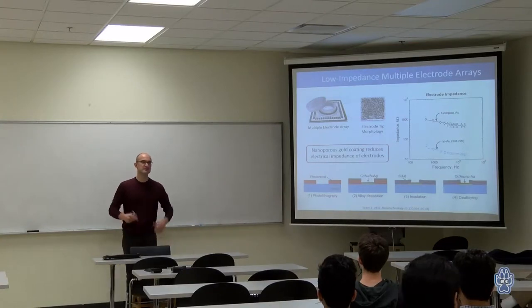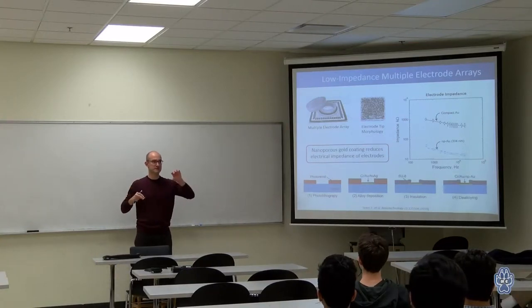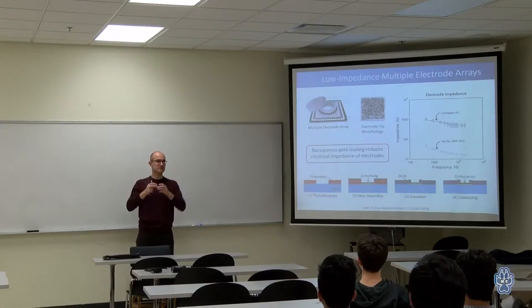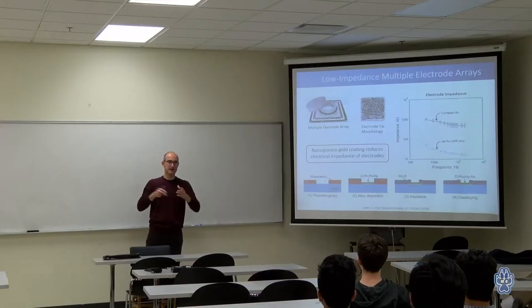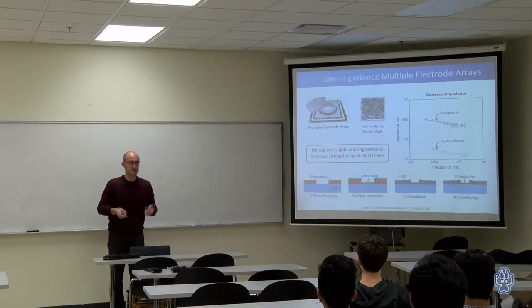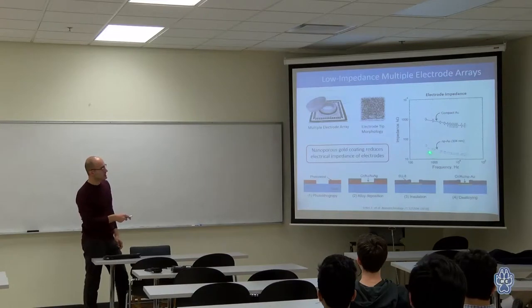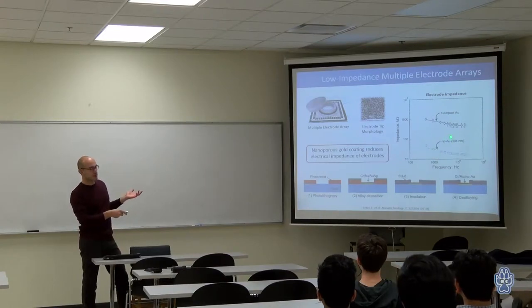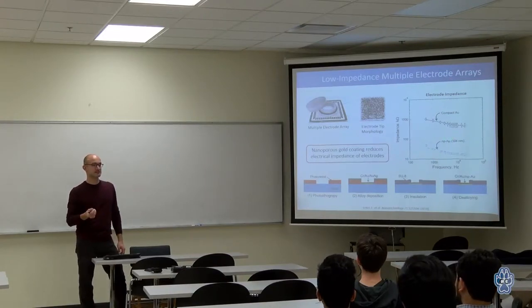And it's actually, this is Randles cell. So you have a resistor and a resistor and a capacitor in parallel. So you are actually increasing the capacitance by increasing the surface area. And at higher frequencies, basically, it reduces the electrical impedance. So this is good from an electrical point of view. But you need to verify this biologically.